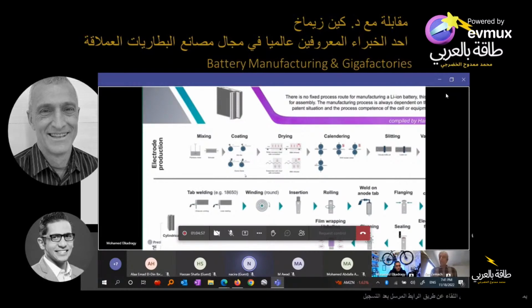You make it too small and you don't get good adhesion, and your electrodes fall apart, either immediately or 300 cycles down the road. So there's a big tug of war in minimizing the binder content. The other thing, but this is where batteries start to get hard. So you say, okay, Ken told me I've got three things. I've got graphite, a conductive agent, and binder. Oh, but the binder's really two different binders. Okay, so I've got four things, and then I need to mix them all together.